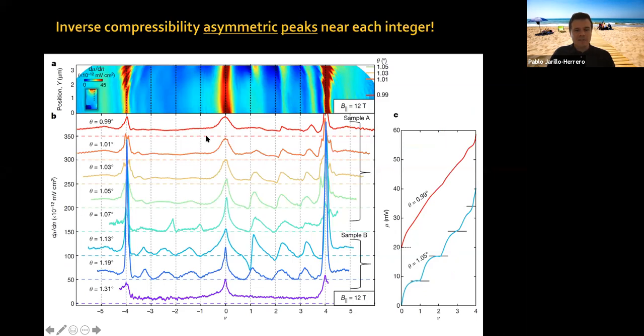So now we're zooming in on this data. This is a measurement of the inverse compressibility as a function of position and filling factor. You can see the filling factor axis here: 0, 1, 2, 3, 4 electrons per moiré unit cell, 1, 2, 3, 4 holes per moiré unit cell. You can see how these features, now that they are normalized to filling factor, all fall along straight lines, okay? The most salient features are these large peaks and the central peak at charge neutrality.